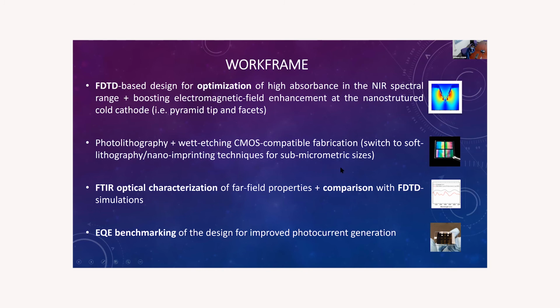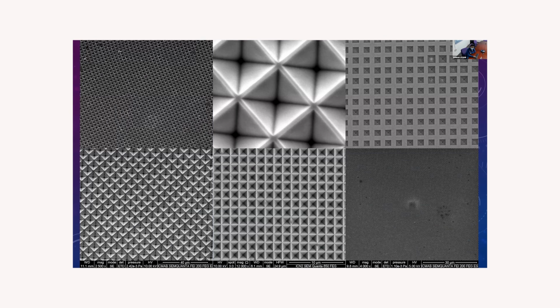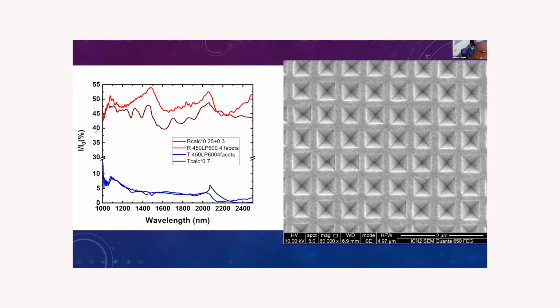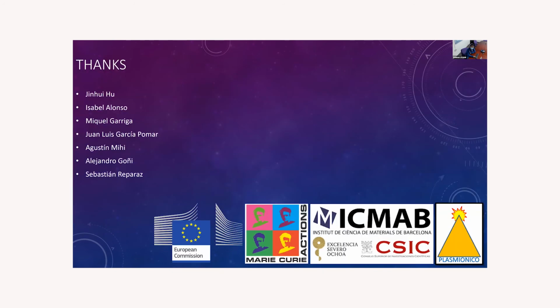Then, using a combination of chemical and physical procedures, we get the structures, and then we correlate the expected spectra with the calculated one, and finally, that is the more challenging step, to extract some current from that kind of structure. We already have a lot of very nice structures, and we also have a very good correlation between the optical properties of the structure covered with gold. So now we are in the last and most challenging step, which is to get some current from this kind of structure.